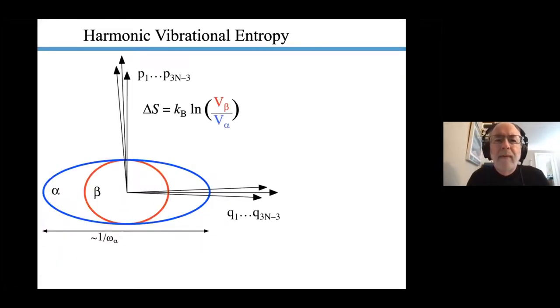So how do we account for the harmonic vibrational entropy, that big red part that was on that previous graph? It depends on the coordinates of the material, and we have uppercase N atoms in our crystal, and in three dimensions we'll have 3N positional coordinates minus the translational degrees of freedom. The idea is that every atom has a range that it's exploring in its vibrations going back and forth here, and the bigger the range, the more equivalent ways of finding the system. For a harmonic oscillator, that's pretty simple. It just goes as 1 over the frequency. So the lower the frequency, the wider we move, and the bigger the entropy.